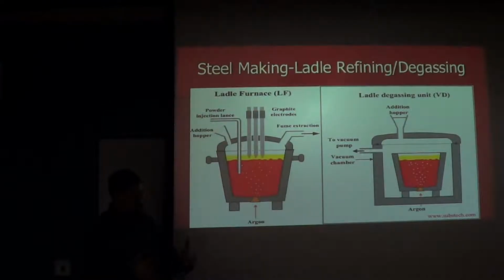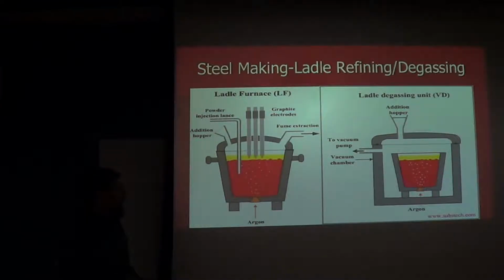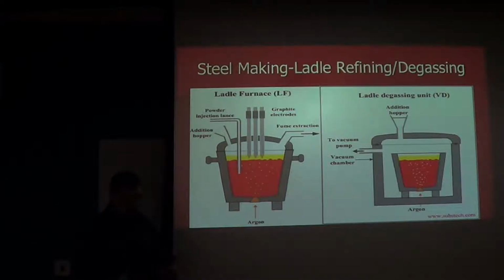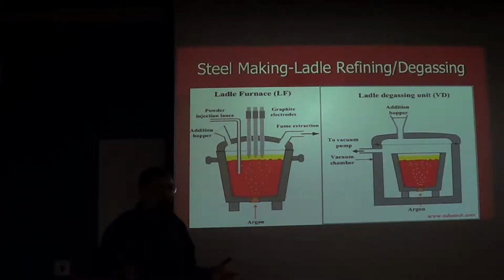Once you're in the ladle, you can do whatever you need to do with it, and one of the reasons for doing that is because now that frees up your furnace to melt another batch of metal. So the mills that are set up that way tend to be fairly high output. You're in the ladle, you've made your alloying additions, you're nearly done, but you need to make sure you get rid of dissolved gases. So that's going to be any of the gases that we have in our atmosphere, oxygen,